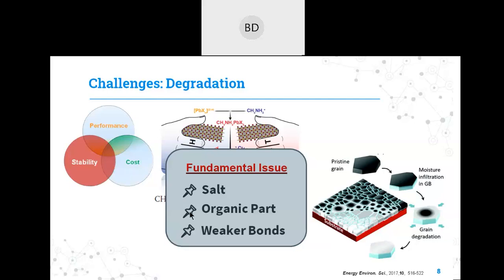The second obvious reason for the MAPbI3 perovskite is its organic part. The organic part, which is methylammonium, is very hygroscopic in nature, so it has a tendency to attract water itself. And the third reason, as we discussed earlier, is the weaker bonds. We have dipole-dipole interactions and hydrogen bonding, which are weak van der Waals forces and very easy to break with some external perturbations. So these are the basic fundamental issues which govern the degradation of the perovskite.